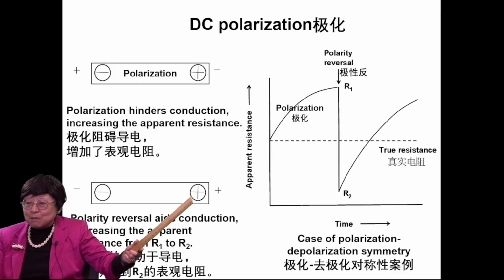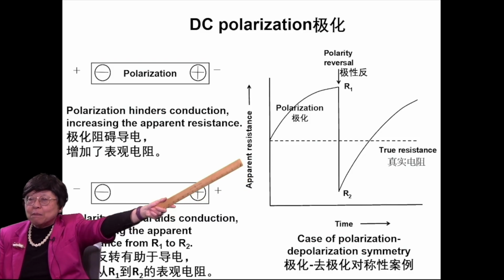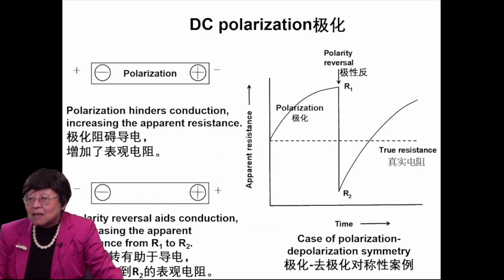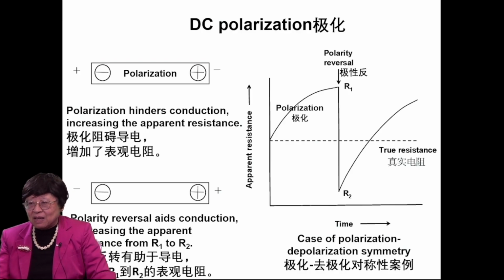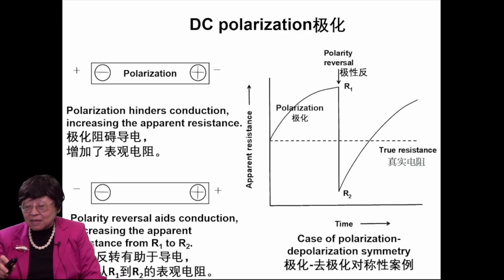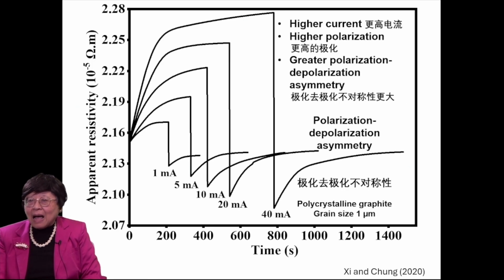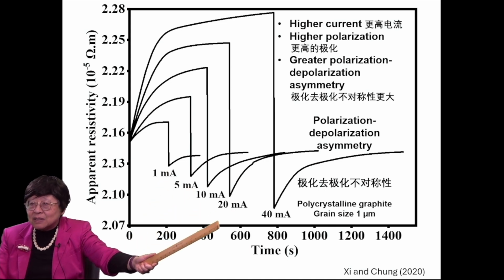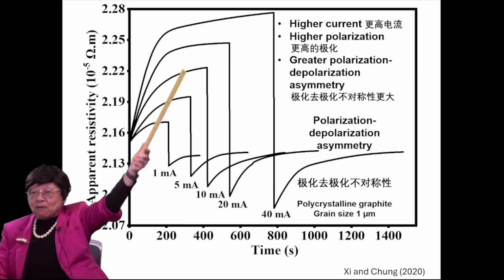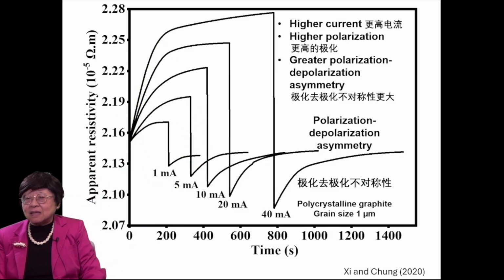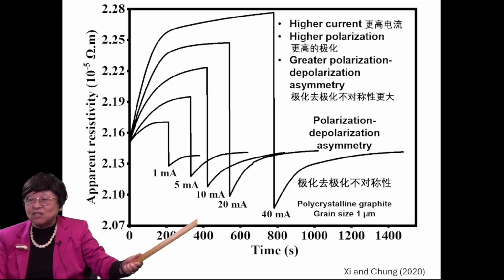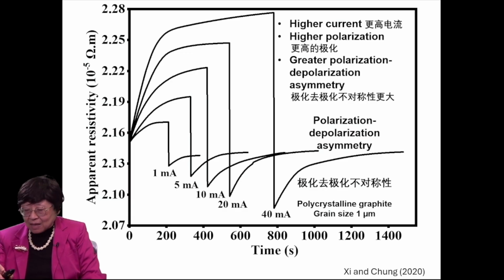And I showed you this before, and this is a case of polarization, depolarization, symmetry. You see the curve R1, R2 is symmetry. We call it polarization, depolarization, symmetry. Okay. However, in reality, it's not symmetrical. This is for polycrystalline graphite at different currents. The higher the current, the higher the polarization. Okay, so the higher the apparent resistivity, and the greater this asymmetry, what I call polarization, depolarization, asymmetry.